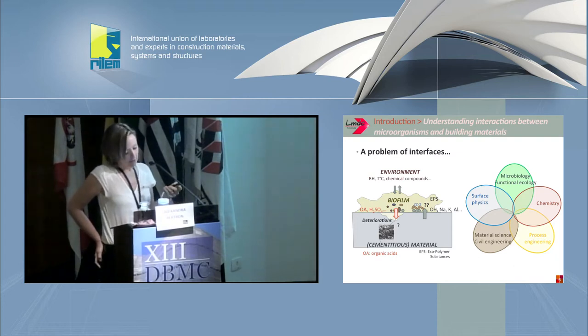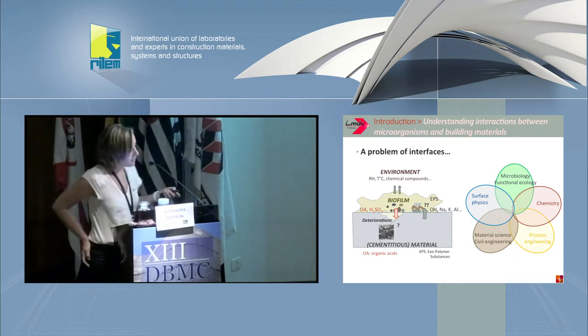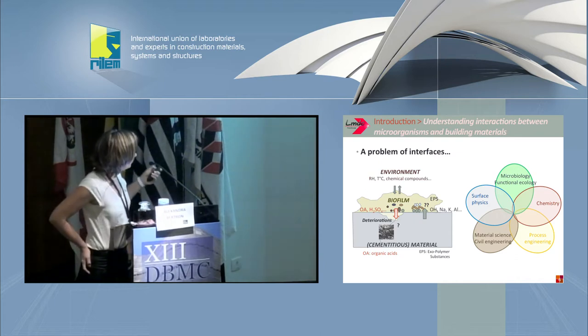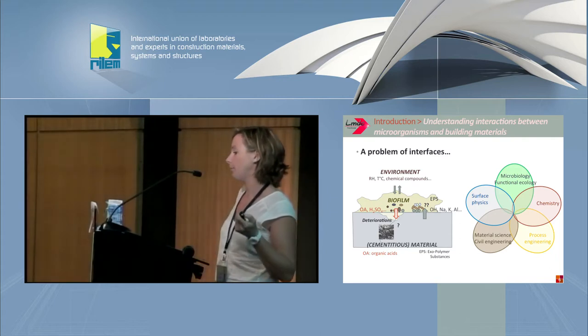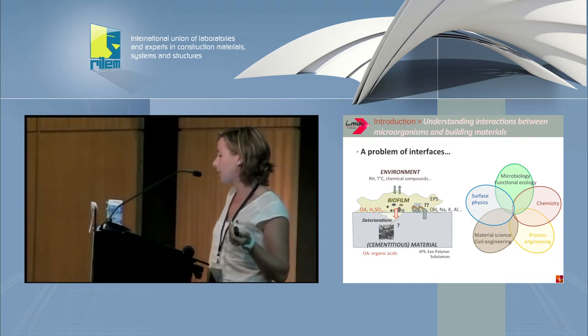But another important point is the action of the material on the biofilm. Actually, for example, cementitious material will release alkaline ions, aluminium, and this release will condition the formation and the structuration of the biofilm, and then condition the aggressiveness of the biofilm on the material. So understanding these interactions is really necessary to develop concretes that perform well in these environments.